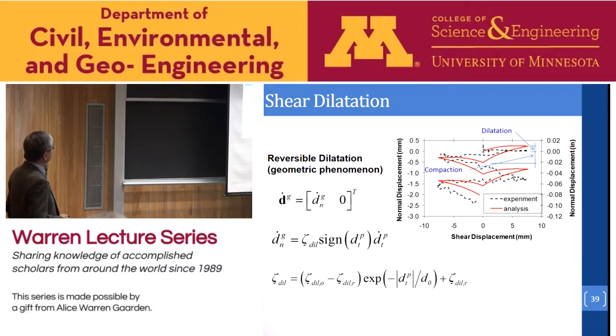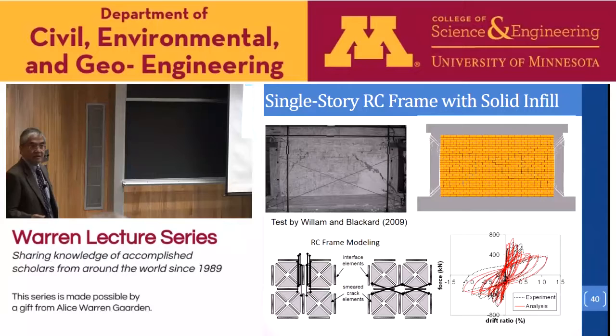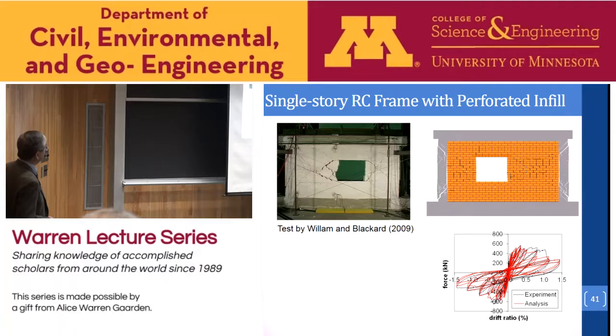So we validated with testing like a single bay infill frame test. There are some tests conducted in Colorado, which is based on a prior research project in collaboration with University of Colorado, also Stanford University. So we can capture the load versus drift ratio quite well. And this is also a case of a specimen with a window opening.